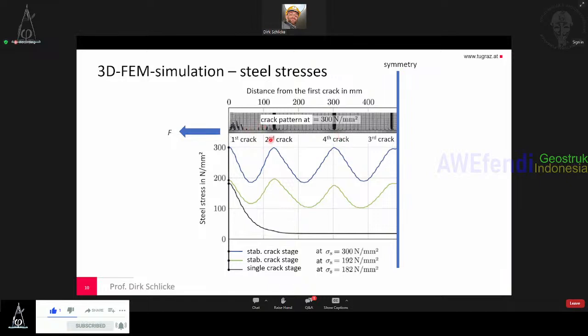The occurrence is not controlled via a scatter of tensile strength. The occurrence is only somehow random, even though there's no scatter of tensile strength. And after producing all 4 cracks, you see this crack is not really open. We still get some force transfer over the crack. But if you increase the force still, then all cracks are open. The steel stresses in each crack are similar to each other. And in between the cracks, we have the tension stiffening effect.